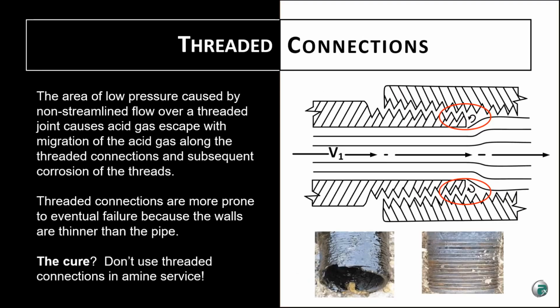Threaded connections are generally not seen in amine service, but in some older facilities that we visited, they are still present. The area of low pressure caused by the non-streamlined flow over a threaded joint causes acid gas escape with migration of the acid gas along the threaded connections and subsequent corrosion of the threads. Threaded connections are more prone to eventual failure because the walls are thinner than the pipe. And the cure then is obviously don't use threaded connections in amine service.